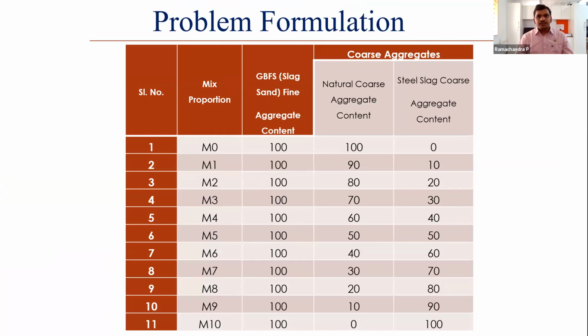So we had taken the fine aggregate completely replaced with the granulated blast furnace slag, and we have used the coarse aggregate as natural coarse aggregate in the replacement. So we had 11 mixes, starting from M0 to M10.